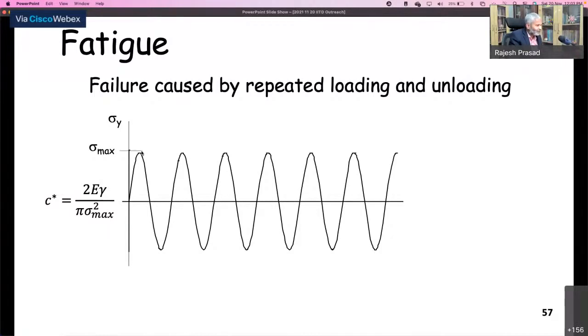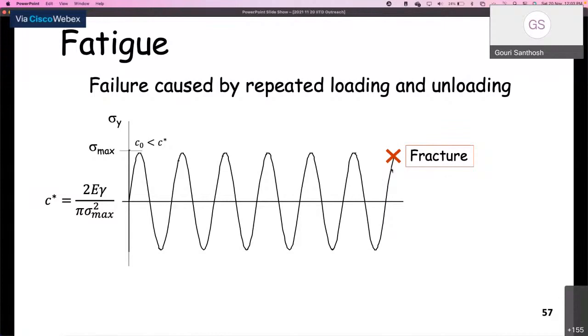And since it is not failing in the first cycle, you know that the initial crack size is less than the critical crack size. So if the crack size is less than the critical size and it is safe in the first cycle, it should be safe for any number of cycles, second, third, fourth, fifth. But what you see is that after a certain number of cycles, at the same maximum stress, it fails. Fracture happens. Fatigue happened. The material got tired of loading and unloading. How does this happen? Griffith's analysis cannot explain that, because we have seen that C0 is less than C star.